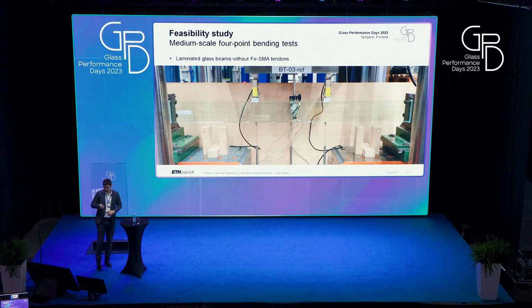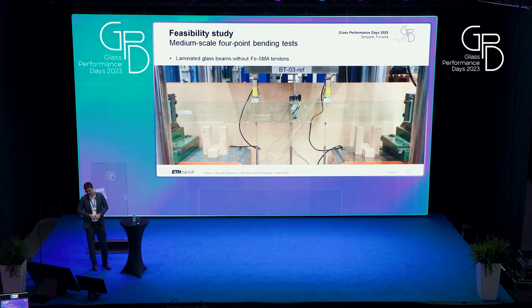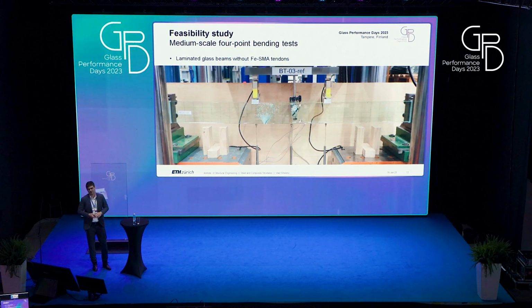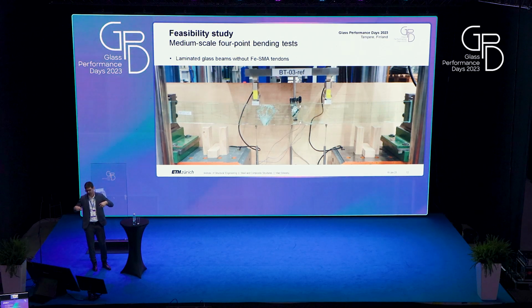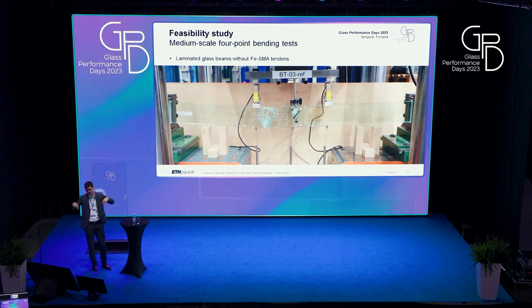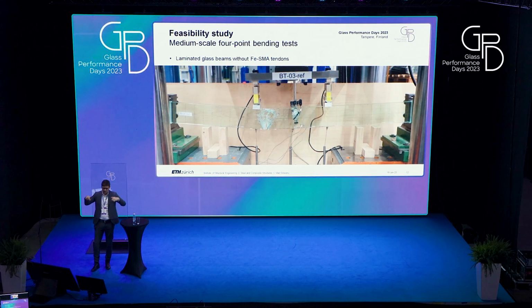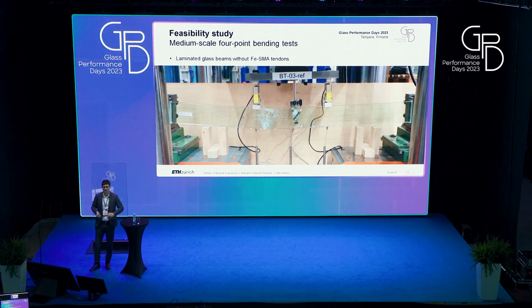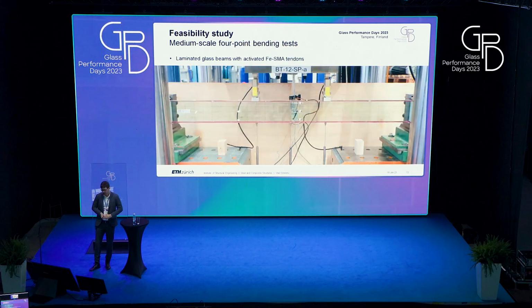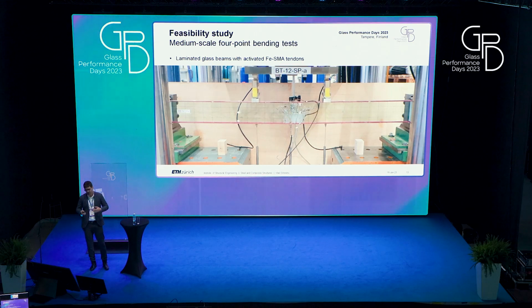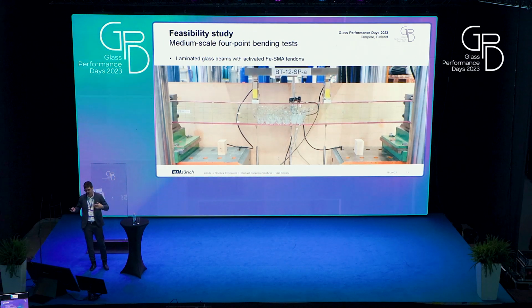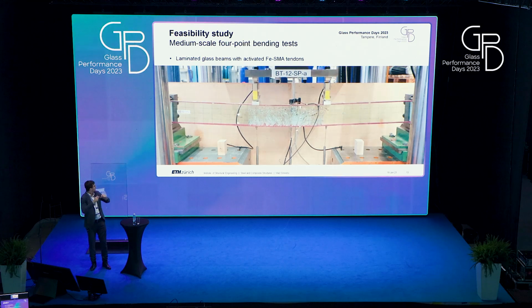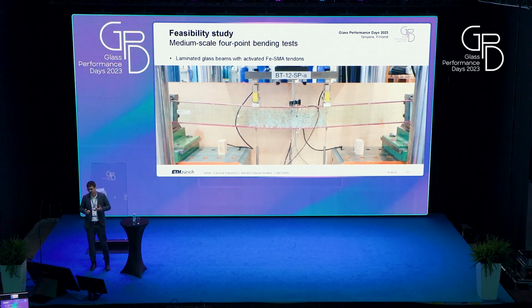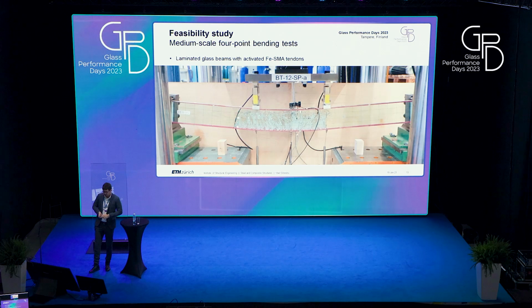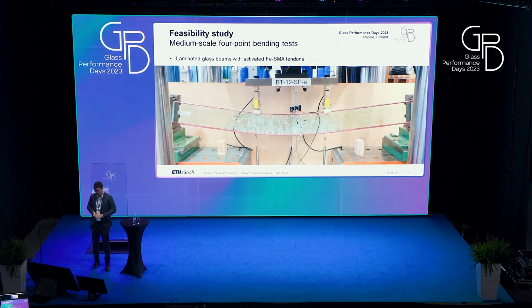In terms of test results, I will show you 2 videos. One for the classical laminated glass, where you have a first crack, and then if you increase the displacement, since the tests were displacement controlled, you will be able to increase the displacement until also the interlayer will fail. If we look at the post-tensioned glass beam, we have a first crack, then a lot of additional cracks. And if you look at the top part of the beam of the glass, this is still intact. So this is qualitatively what happens.